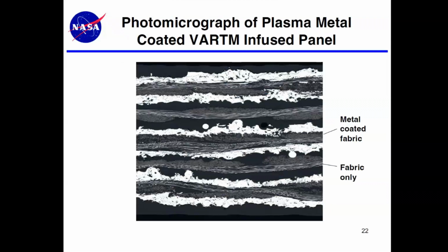For example, here we coated both sides of several different fabrics. We set the parameters of the deposition process so that we only melted the outside of the particles and didn't fully melt the particles. So we were able to put a porous layer of metal onto the fabrics. That allowed us to then infuse through that porous layer.